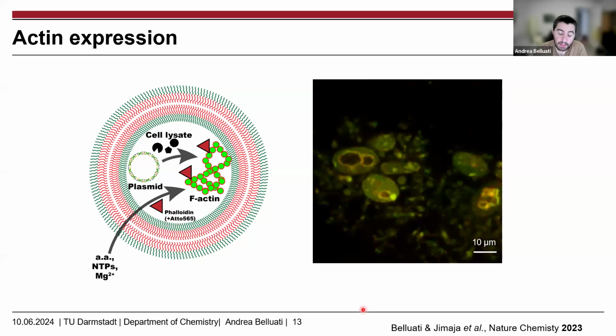And this was quite puzzling because we didn't get the filaments we were expecting or some kind of networks, but we got what may be gel phases, interacting in a weird way with the membrane, even forming internal compartments inside, pinching off the membrane from the cell. However, we didn't investigate this behavior as much as we would have liked, but still we could see the production of actin and its polymerization using an osmotic shock with magnesium inside.